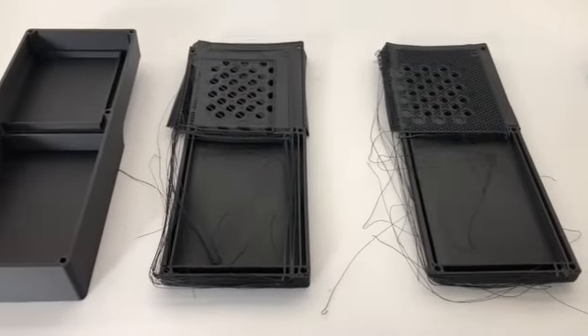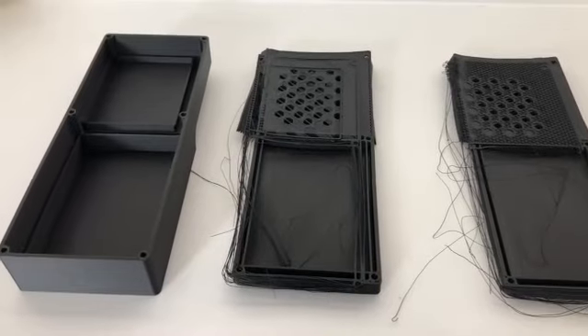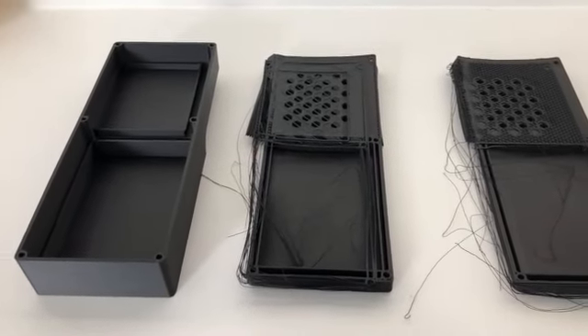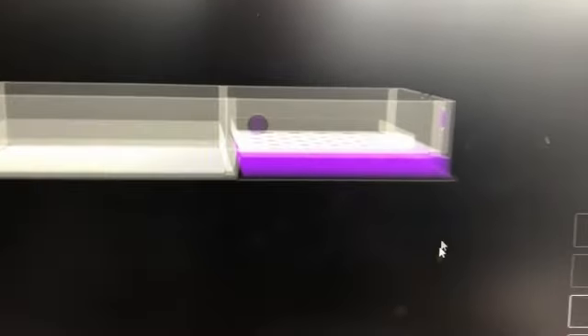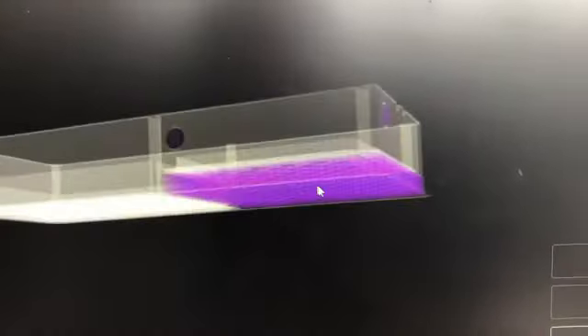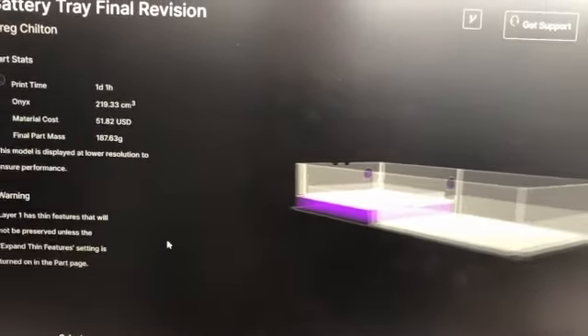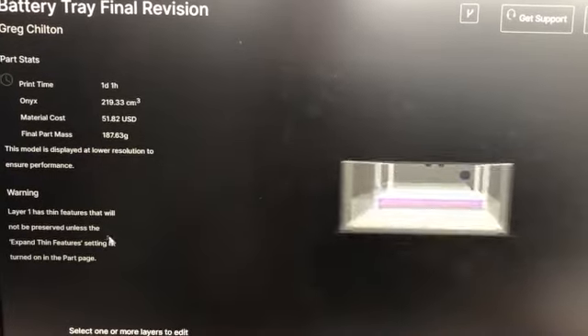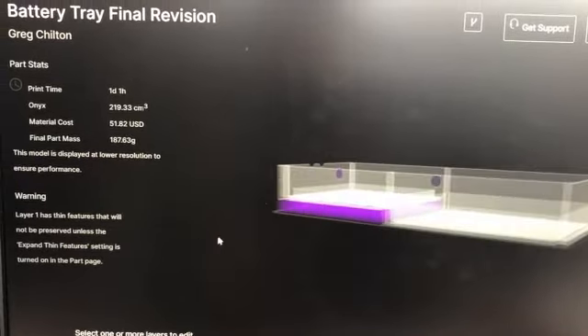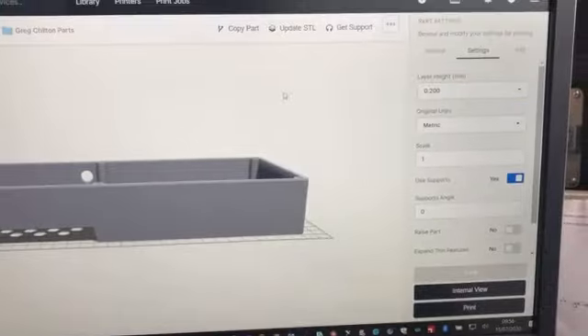However, unfortunately, the additional cooling vents were in the same print region as the printed support structure. I did not evaluate the printed support structure design effectively, which resulted in 2 failed prints after the design collapsed due to the addition of the cooling vents. I carefully re-evaluated the AM support structure design, print layer and wall thickness settings to optimise the print to further prevent collapses.